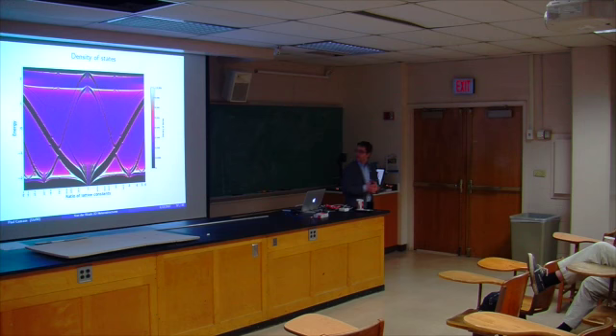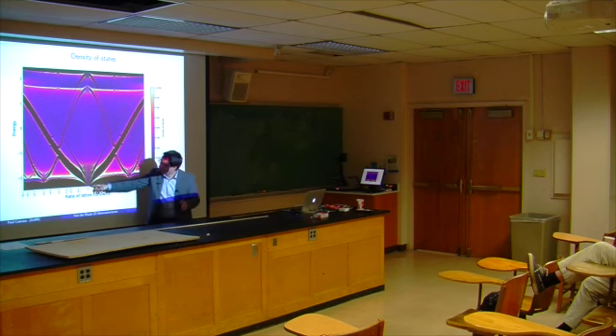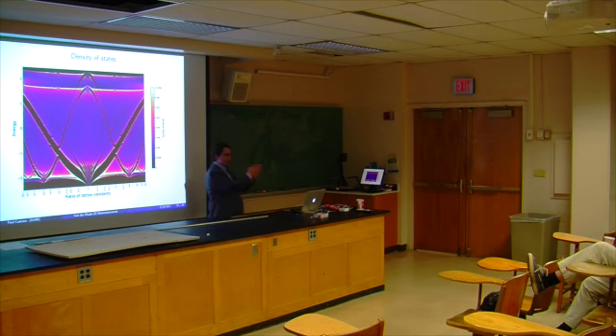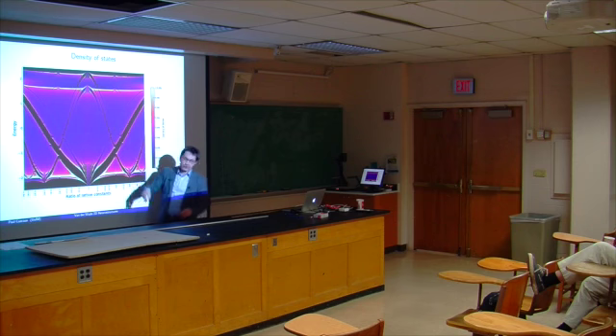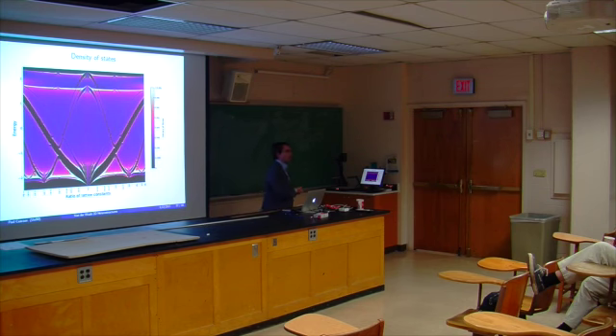Yes. The natural way to look at these band gaps is that they appear because of some large periodicity. We know that a large periodicity translates into a very small Brillouin zone, and that gaps will appear at the edges of this Brillouin zone. So especially when we are slightly away from 1, the periodicity appears at very large length scales, and therefore we see lots of little gaps appearing because the corresponding Brillouin zone is very small. The fact that this one is the biggest and survives for longer is probably parameter dependent. I wouldn't be able to really explain why that is.